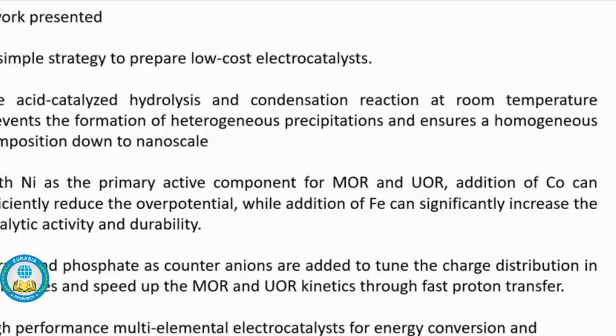This work presented a simple strategy to prepare low-cost electrocatalysts with nickel as the primary active component for MOR and UOR. The addition of cobalt can efficiently reduce the overpotential, while the addition of iron can significantly increase the catalytic activity and durability. And these are high performance multi-elemental electrocatalysts for energy conversion and production of value-added chemicals.